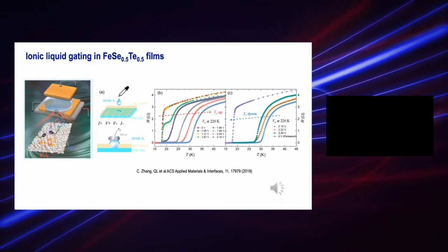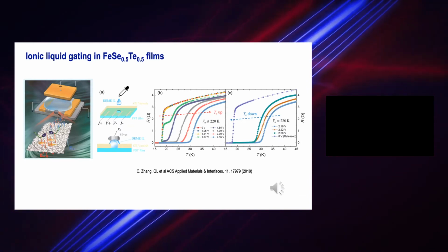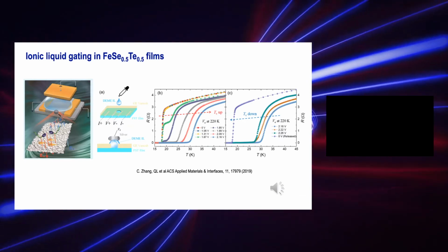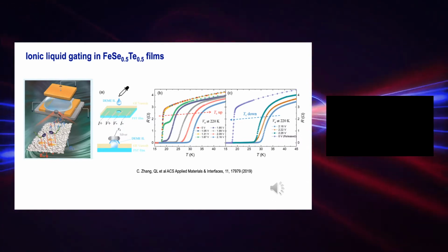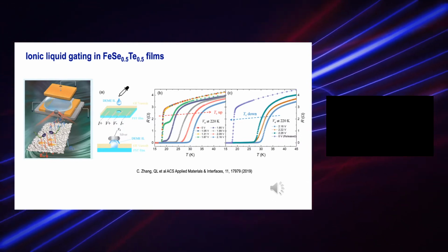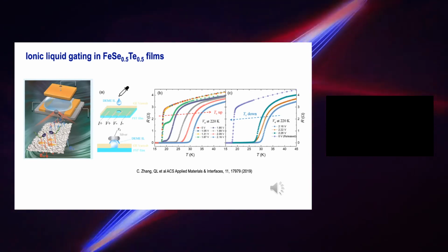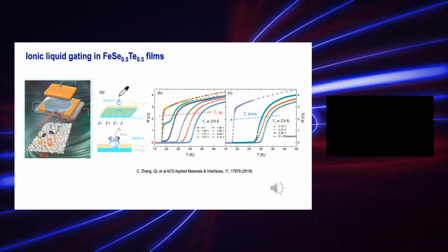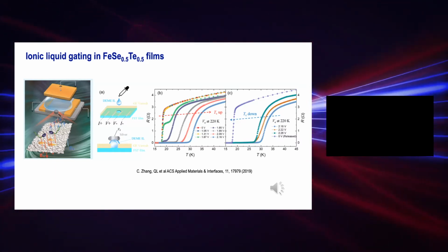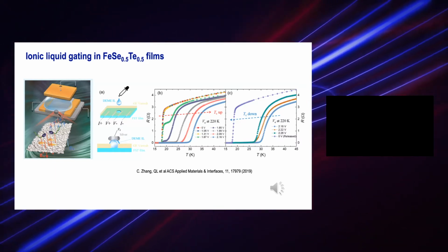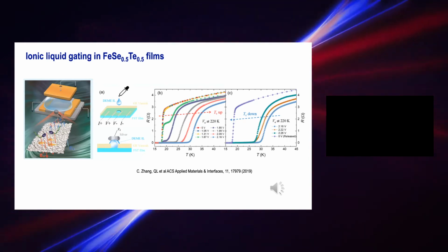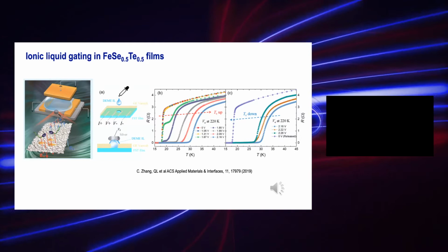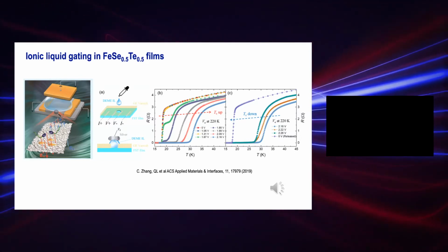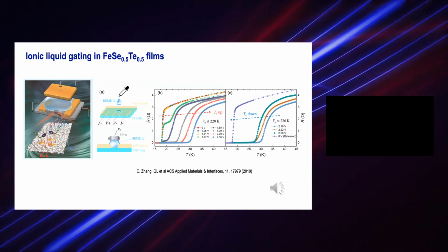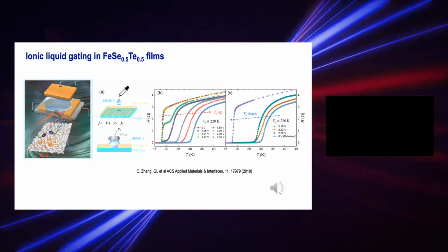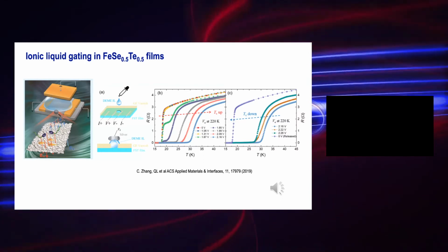It's also amazing to know that ionic liquid gating can enhance the TC of iron chalcogenide films dramatically. Shown here is an example done by my former student, Chen. He put the ionic liquid on top of these iron chalcogenide films and applied a gating voltage. As you can see, a TC of more than 30 kelvins was achieved in gated films. If you release the gate, TC goes back down and recovers the original behavior. This kind of reversible doubling of the TC could be very interesting in future studies.